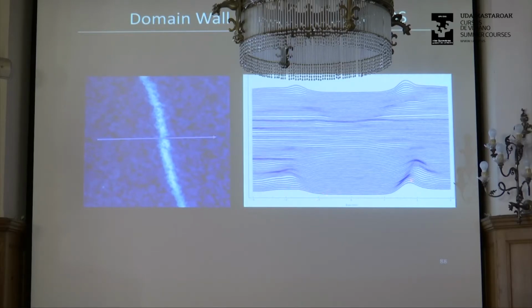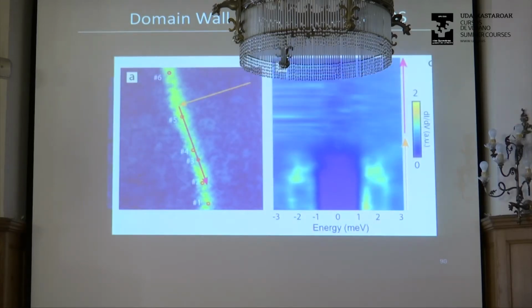But you can see the superconducting gap, and as you go across the domain wall, it's actually the same data. You see a flat density of states. Here is a color plot of the same thing. If you go across the superconductor, you see the superconducting gap. Density of states is suppressed. And as you go along the domain wall, you see a sort of featureless density of states inside the superconducting gap.